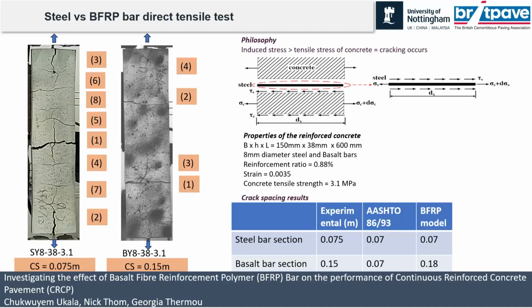and we pulled them. We believe that the philosophy or the thinking behind it is that for steel, for the CRCP, we know that the concrete will shrink, the steel provides a resistance to it, and stresses develop and cracks occur. So in this case, we put the steel, and we expected the concrete to provide a little resistance. Stresses will develop. When the stresses are greater than the tensile strength, cracks will occur. And we were able to get some level of transverse cracks like this.